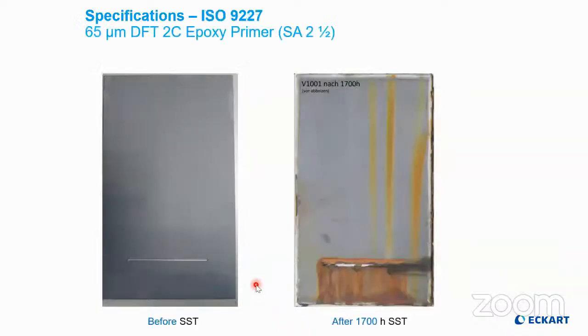But I want to show you in this slide a ZincFLAKE epoxy primer, 2-component, on sand-blasted steel SA2.5 at 65 microns after 1,700 hours salt spray test. And you see this paint film before salt spray test exposure, and you see the same panel after 1,700 hours salt spray testing. And once again, there is a red rust formation here at the scratch, but no creeping underneath the paint film.